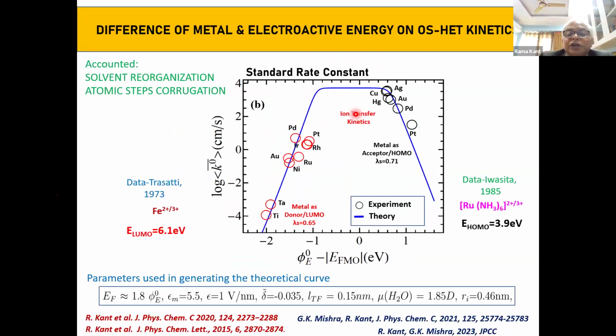And this is the same plot with data. We have accounted for solvent rearrangement. We have also accounted for atomic step corrugation, because it's a solid metal. This data did not provide us that, so we have put some average level of atomic steps in all calculations. And here is data of Trasatti and another of Iwasita, where various metals are plotted over it. And this is my theoretical curve, and it is plotted as a continuum.